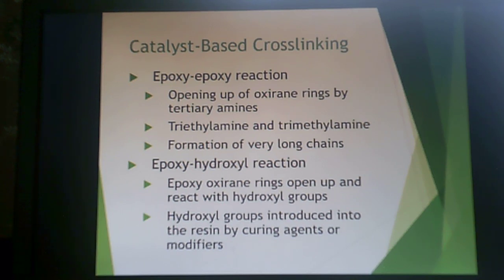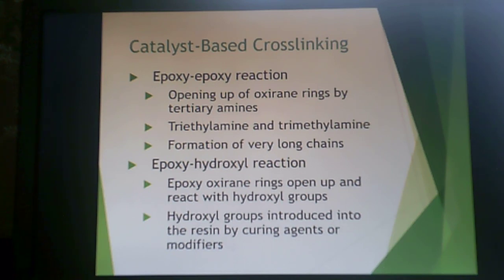In catalyst-based cross-linking — that's your epoxy-epoxy reactions or epoxy-hydroxyl reactions — you open up the oxirane ring using typically tertiary amines, such as triethylamine or trimethylamine, and you can form very long chains this way. In an epoxy-hydroxyl reaction, the epoxy oxirane ring opens up and reacts with hydroxyl groups, and the hydroxyl groups are introduced into the resin by curing agents or modifiers.